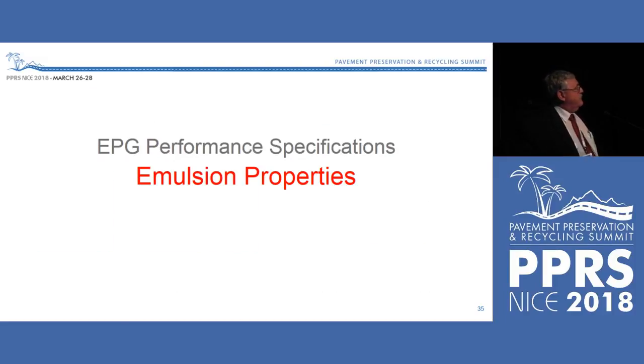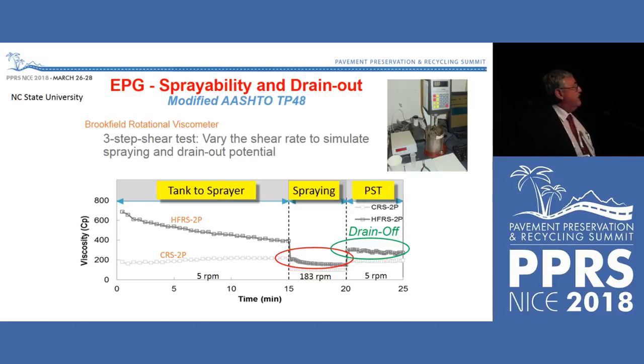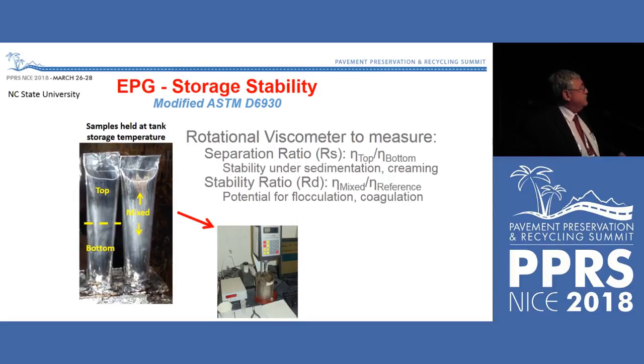There are a lot of different emulsion properties. Richard Kim's developed the methods to look at shear rates in pumping during spraying, and finally the shear rates on the road, whether material runs off the road into the low areas or whether it stands up for cracking. So we have a much better perspective, as Bernard suggested we need, for using shear rate on emulsions. Storage stability, totally different things.